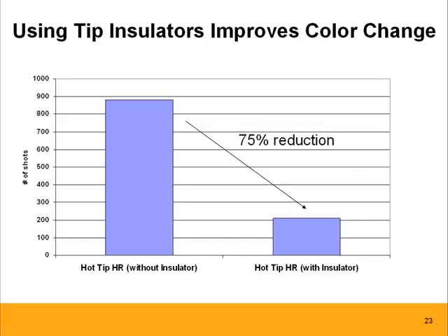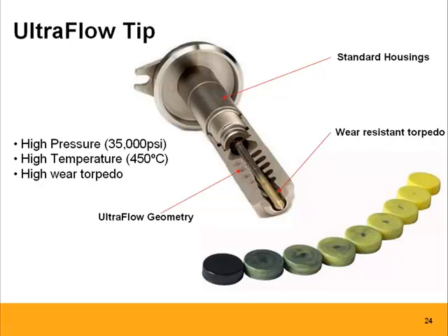The other thing I would like to talk about, as sort of a technical solution to color change, is what Husky offers: a mixing tip. We call it the UltraFlow. What it does is take the resin right before it enters into the cavity and actually mix it. It doesn't create any turbulent flow. We established that because of the Reynolds numbers, we can't do that with plastics. But what we can do is create crossing melt streams, and that's actually what does mix plastics. That's what the tip does.